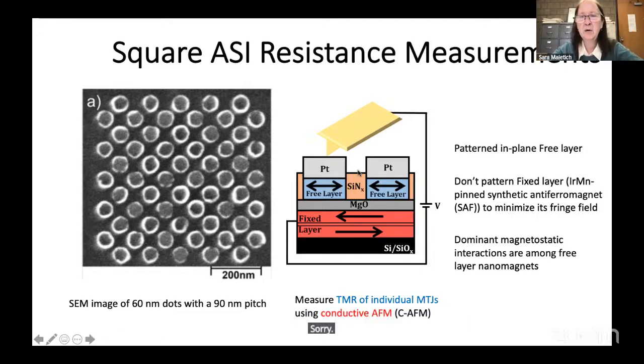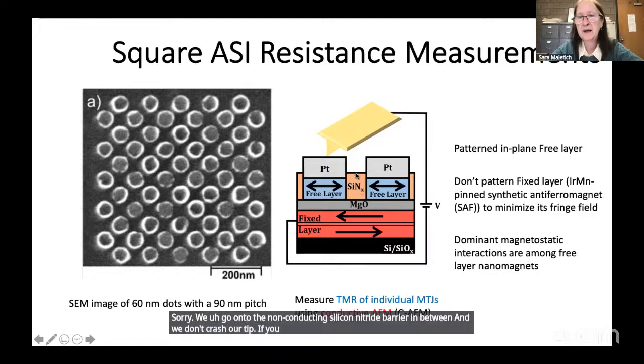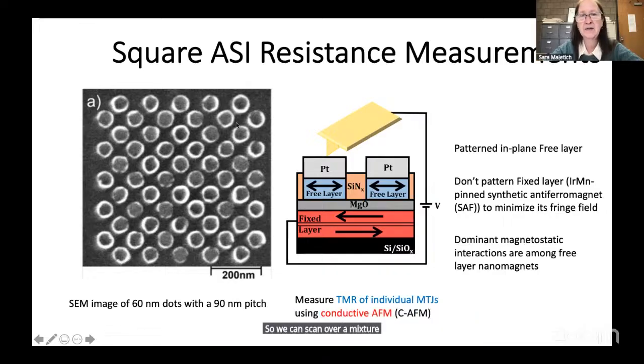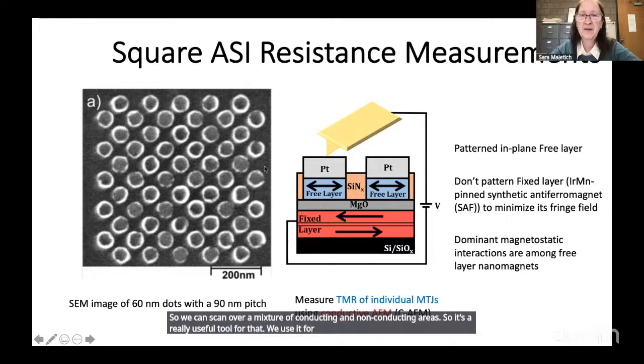We go onto the non-conducting silicon nitride barrier in between, and we don't crash our tip. If you did STM in ultra high vacuum, it would be getting closer and closer to try to get a certain tunnel current threshold, and you wouldn't reach it because this is an insulator. So we can scan over a mixture of conducting and non-conducting areas. So it's a really useful tool for that. We use it for magnetoresistance.